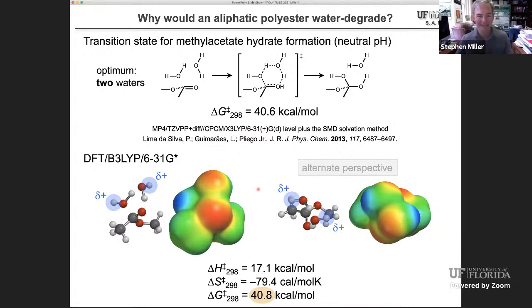We wanted to look at this type of computation, so we mimicked it here at a different basis set and different level of theory, but got the same result. So you end up with a delta G double dagger and a delta S double dagger. Overall, the barrier is about 40 kcal per mole. Essentially, the reason why this is not a favorable process is because you end up with a large amount of charge concentration, that is positive charge concentration, on these hydrogen atoms, which are not part of the 6-membered ring. So you have a lot of charge buildup, and nature abhors charge buildup. You can see that here in this electrostatic potential map by these blue dots. The blue portions just mean you've got charge concentration. You don't have a situation where charge is delocalized, and that costs energy coulombically.